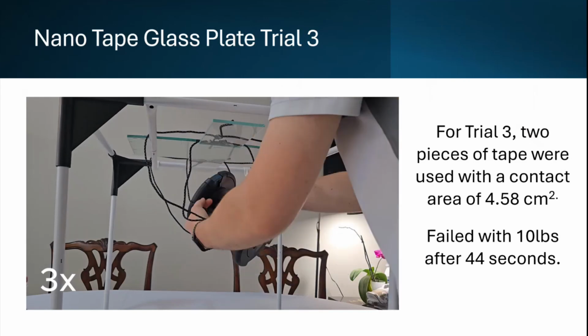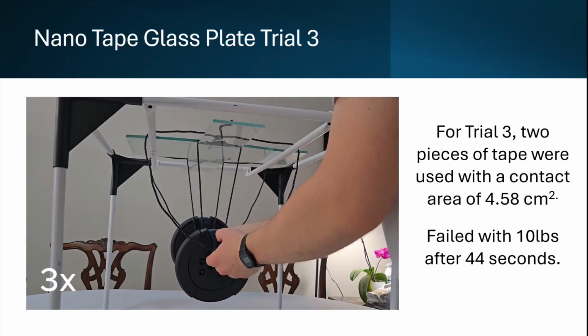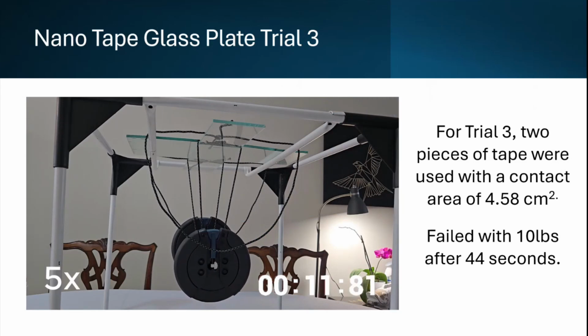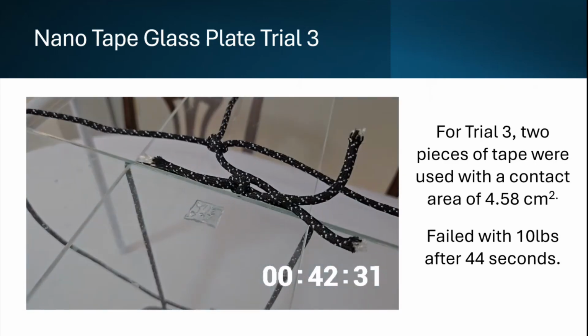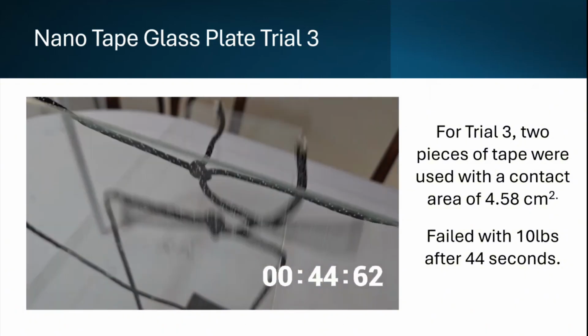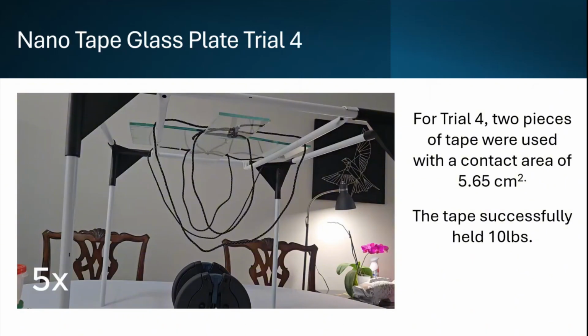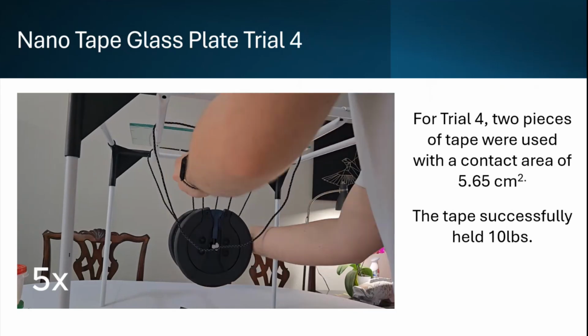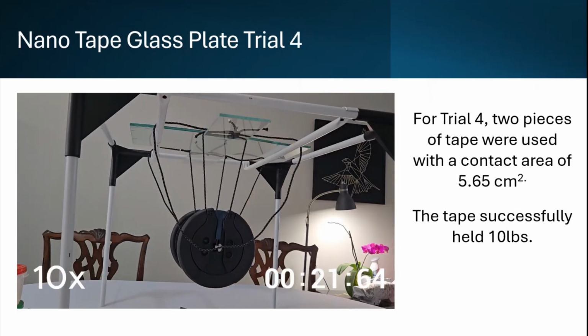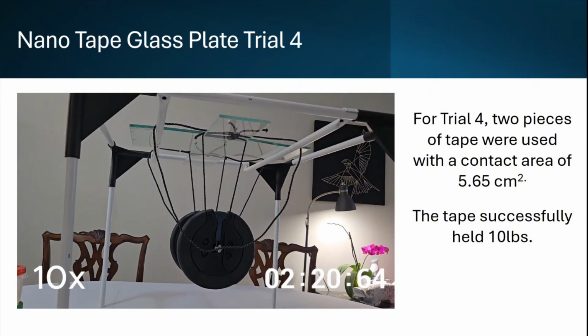And so in trial 3, I used 2 pieces of tape on either side, and in total they had a contact area of 4.58 centimeters squared. These failed after about 44 seconds. You can see this video here is on 5 times speed, and at about 44 seconds, it failed. So here is trial 4. 2 pieces of tape were used with a contact area of 5.65 centimeters squared, and this is kind of a boring video because with 10 times speed, it successfully held the tape. No bubbles were forming as seen visually, so I concluded that this area of tape could successfully hold 10 pounds.